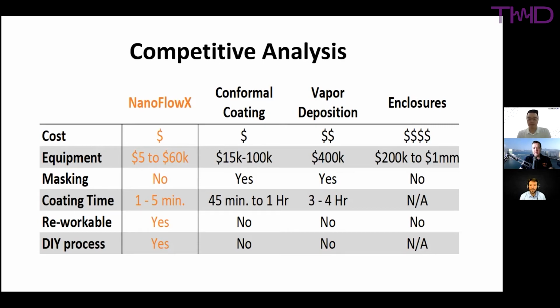So in terms of coating thickness, you mentioned 500 nanometers to 1 micrometer. Can you control that? Does that just come down to the viscosity or surface tension of that solution? Yeah, to get to 500 nanometers, you're going to have to spray. The spray coating will make it much thinner. And then the dip coating, we average at 1 to 2 microns.